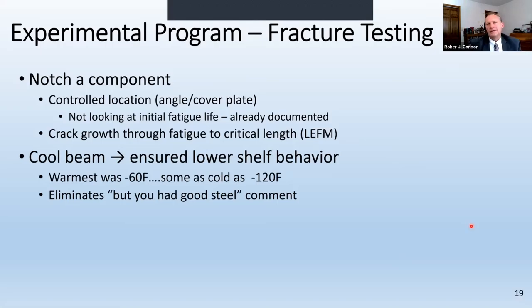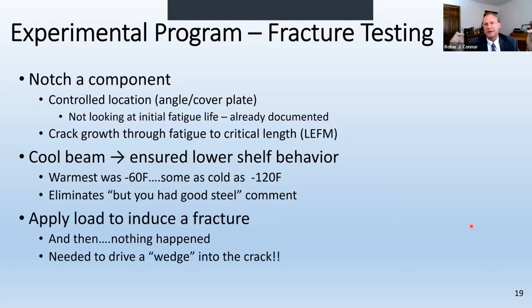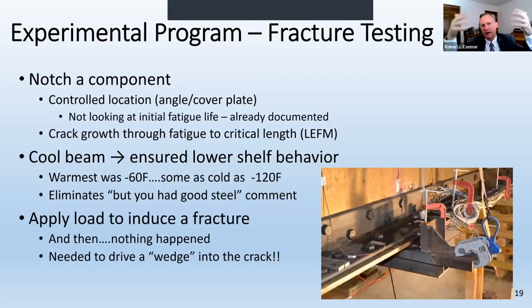So we would pre-crack the steel, calculate a critical crack size, load the girder. And unfortunately, in every case but one, nothing happened. The cracks didn't jump. And that has to do with the compliance of the girder. So what we had to do is actually drive wedges into the crack. So under full load with wedges driven hydraulically, we would drive the crack. And that's because we want to get the big bang, if you will. We want the big energy release to find out if the fracture would have enough energy release to propagate through the other components.